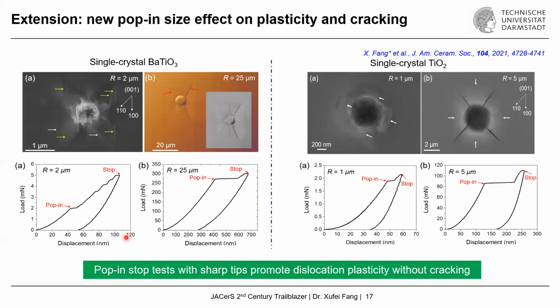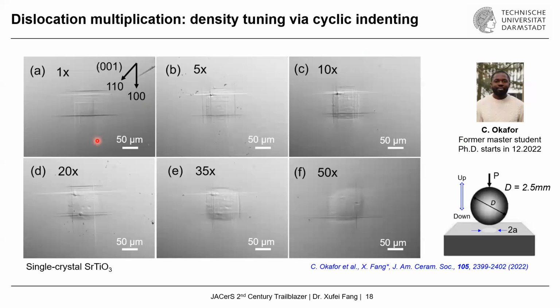It shows consistently that if we are able to engineer a sharp indenter, we will always be able to generate dislocations purely without cracking. But if we go to a certain tip radius that is larger than a critical value, we started seeing both dislocations and cracking. And there is also a very interesting application based on this technique, which I will show you later.